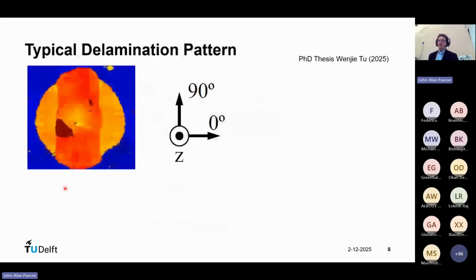And so the typical pattern that you see looks like this. So this is an ultrasonic C-scan image where the color represents the depth through the material. So we see we had an initial delamination here in the center, or initial Teflon inserts, and we see these two distinct delamination planes, because essentially, as Emil explained, immediately at the edge of the inserts, if the fibers are not aligned with the preferred delamination growth direction, the radial outward direction, the delamination immediately migrates until it finds a plane where the fibers are aligned.